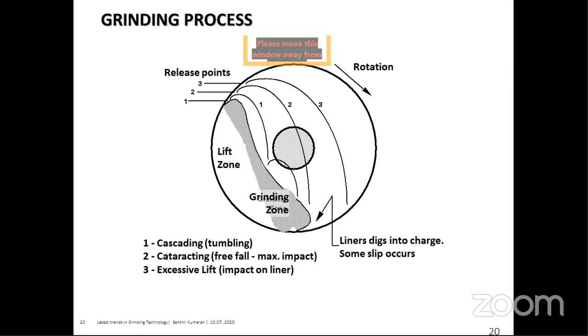So typically when we design this ball mill, we choose up to 77 or 78 percent of the critical speed. That's the point where the effective grinding occurs. As we can see here, the ball mill is rotating in a clockwise direction. If the ball is released from point 1, it cascades, and the second point is where the maximum impact will be.